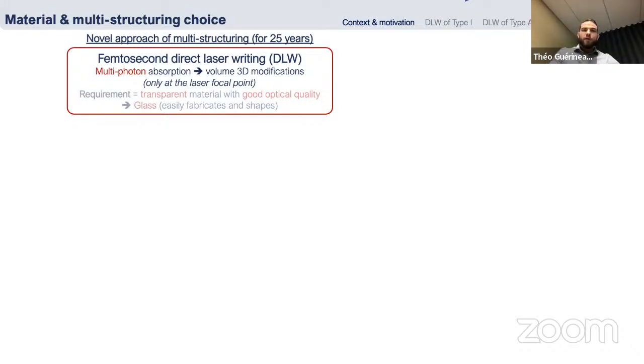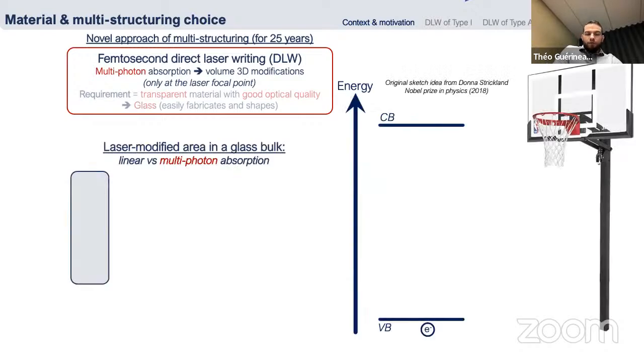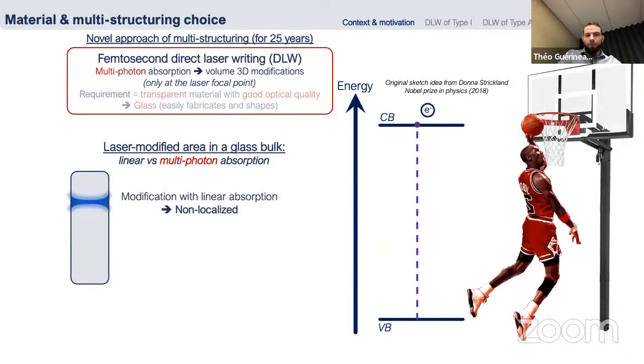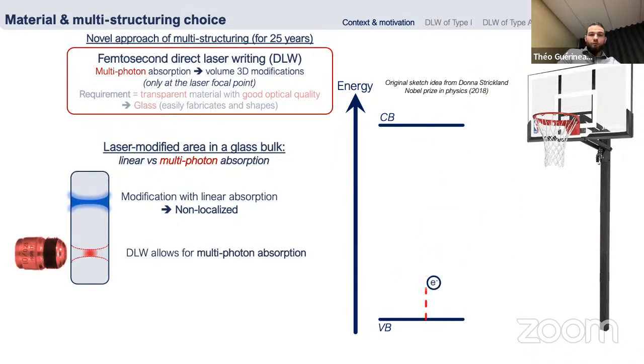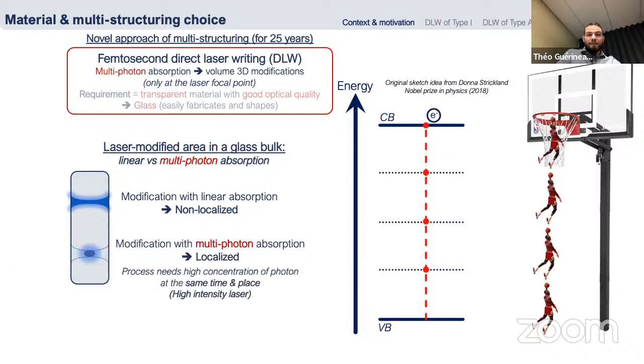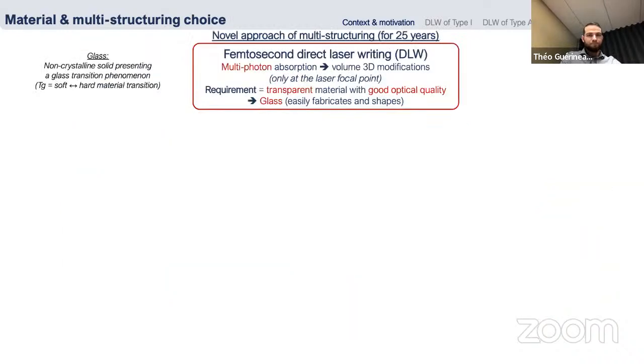So first, let's focus on the multi-photon absorption. On the left, you have the cross-section of one material. On the right side, you have the energy level of this material. And so if you excite your material with a linear absorption, there is an excitation of your electrons, but the modification is non-localized. But now, when you have multi-photon absorption, the modification is no longer non-localized, but rather localized. And to do so, we must use a laser allowing a high concentration of photons at the same time and place.